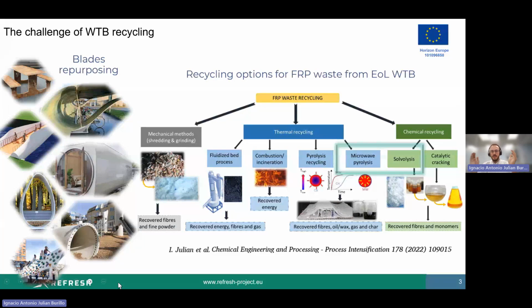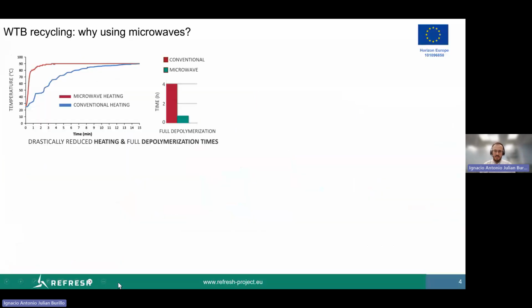So we are more focused on a particular case of thermal and thermochemical recycling, that is solvolysis and pyrolysis. Both technologies are evaluated under microwave-assisted heating. Why microwaves? Because microwaves are able to heat selectively the material that we want to pyrolyze or solvolyze, and decrease the start-up and shutdown periods along the process.